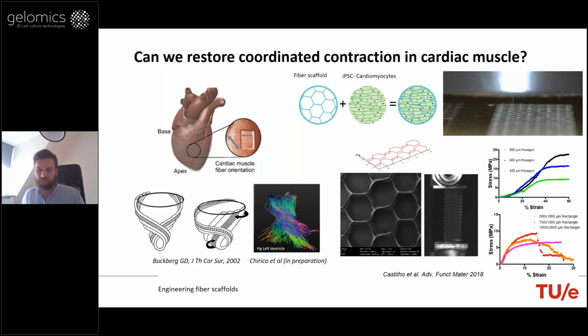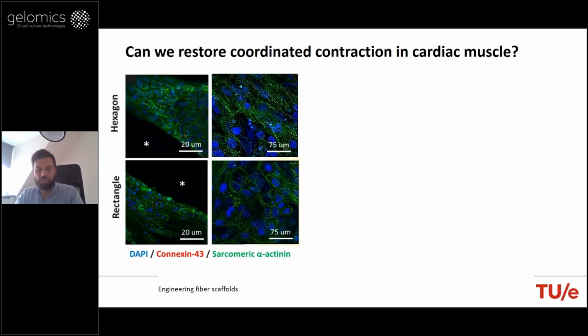We then went further on investigating how the structure could eventually restore organization or not, or induce maturation and alignment of cells, and later on restore organization of the damaged tissue when implanted. We performed immunofluorescent stainings at day 14 of culturing of iPS derived cardiomyocytes in these printed PCL scaffolds. What we showed in these confocal images is that the hexagons showed enhanced alignment, as seen by the sarcomere content, as stained by alpha actinin in green. We also looked at connexin 43 protein expression, which is present throughout the cardiac patches and tells you if they support electrophysiological coupling of the iPS derived cardiomyocytes. And this is stained in red.